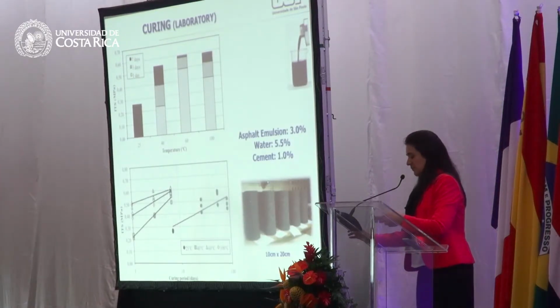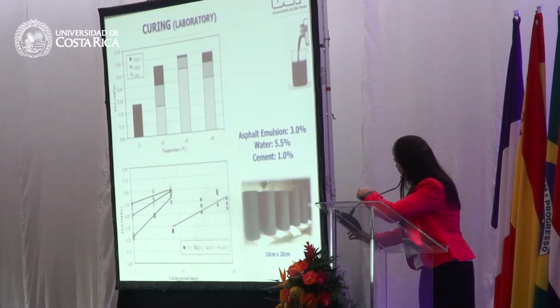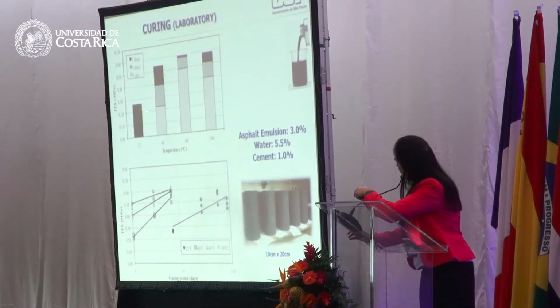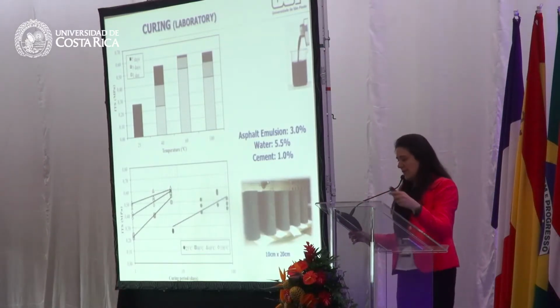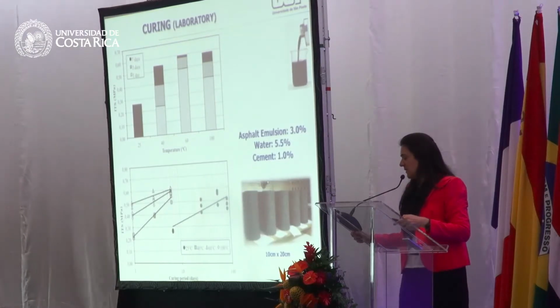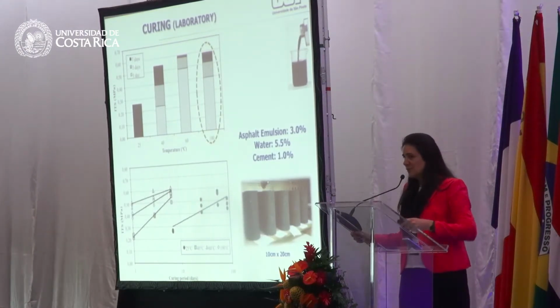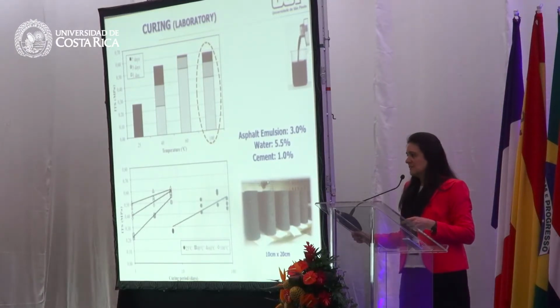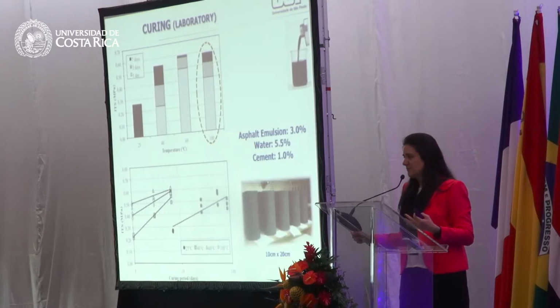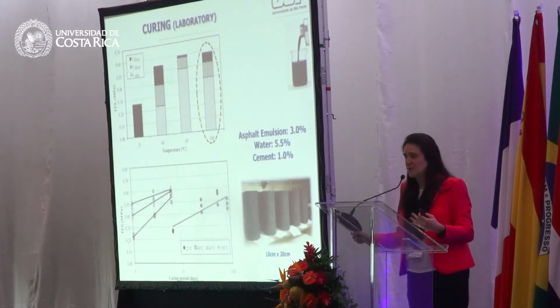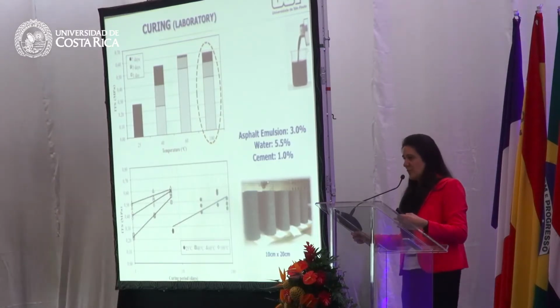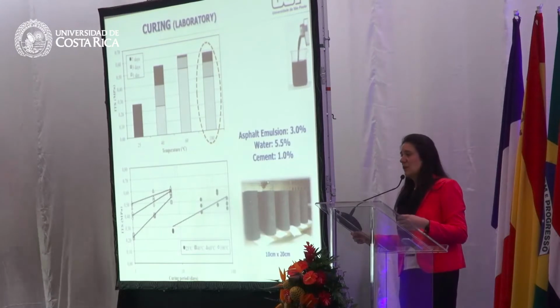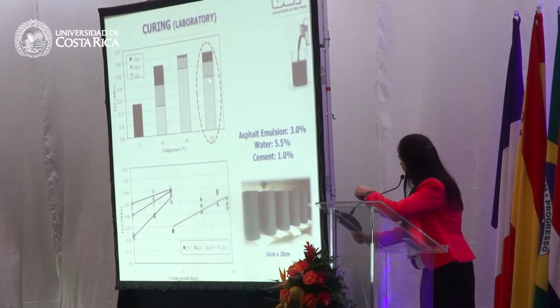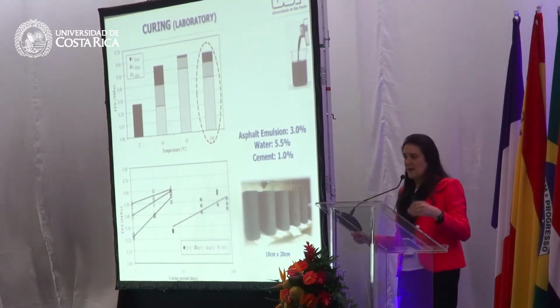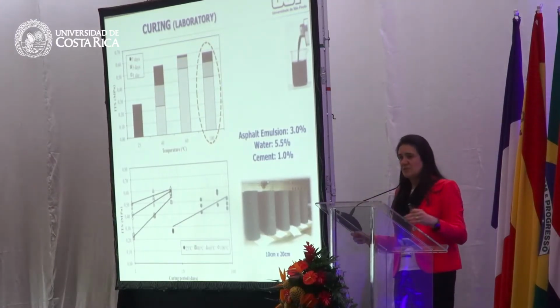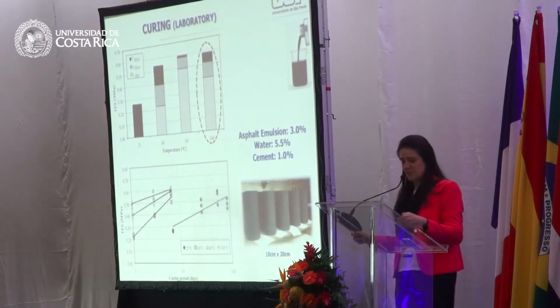And in these plots, we see this is the temperature we've tested, and this is the time. We've run 1 day, 3 days, and 7 days. By the end of this study, we realized that we cannot go up to 100 degrees C. We most probably start degrading this material, changing this material with the heating process. So nowadays, if we are doing cold recycling with emulsion, we do it at 60 degrees C for 3 days. After that time, we've seen, based on different mixtures, that we can reach this stable value in a faster way.